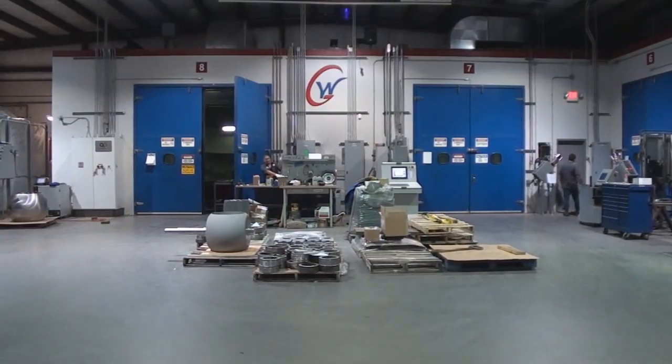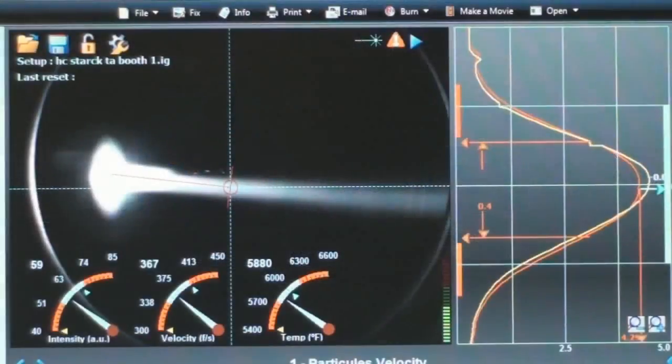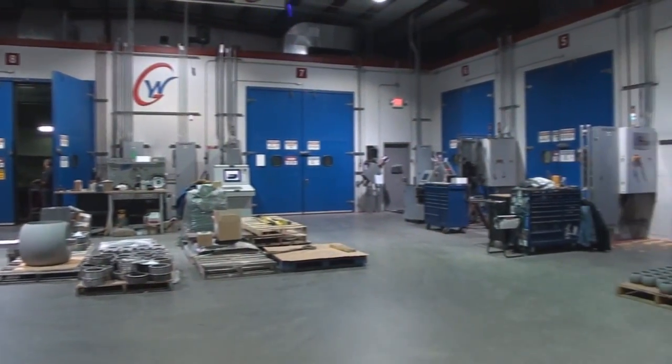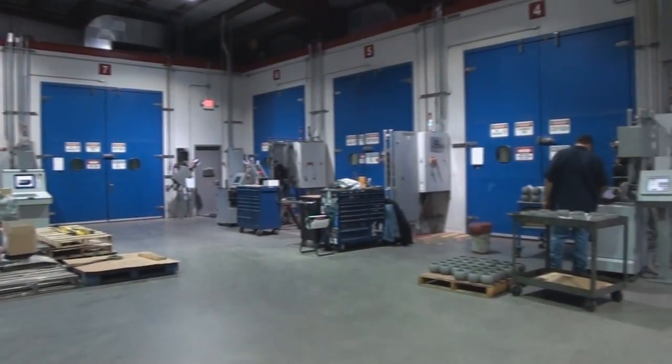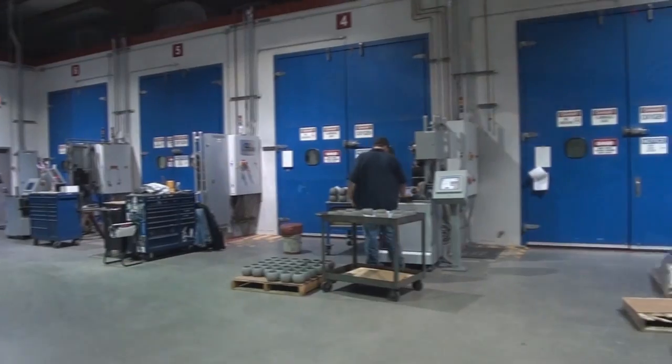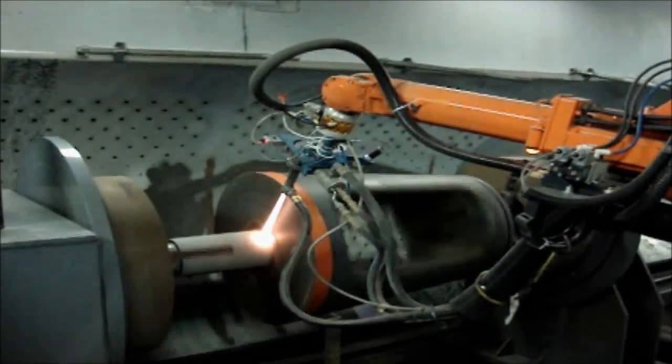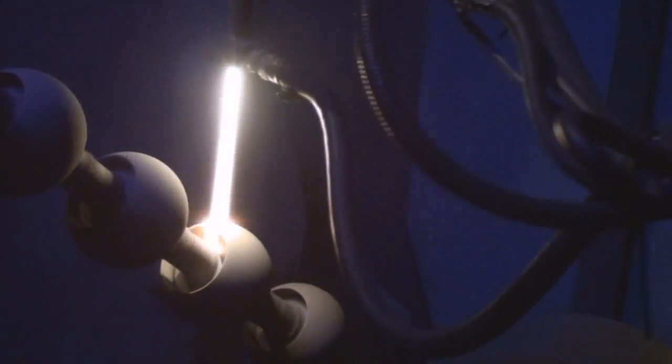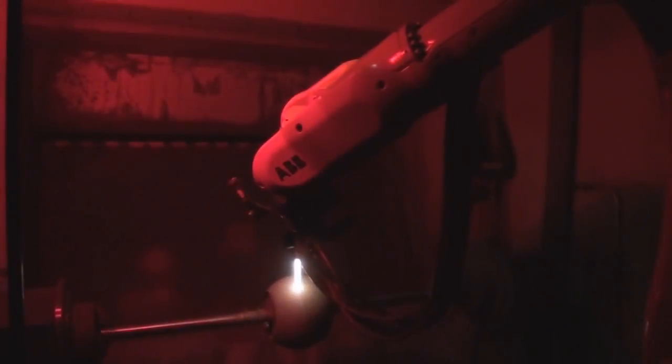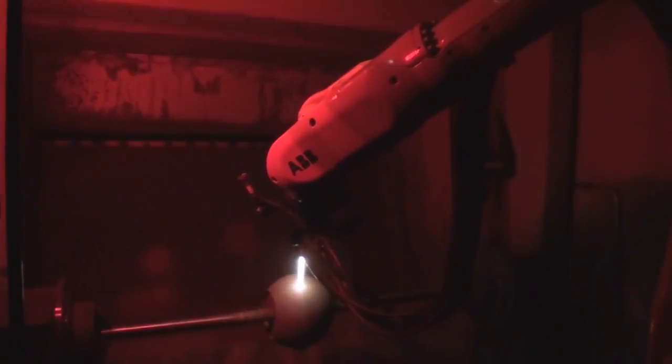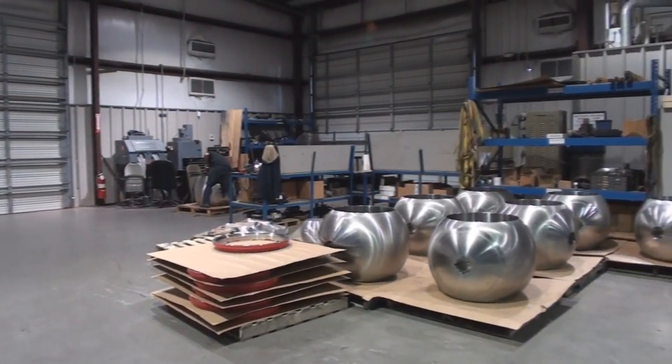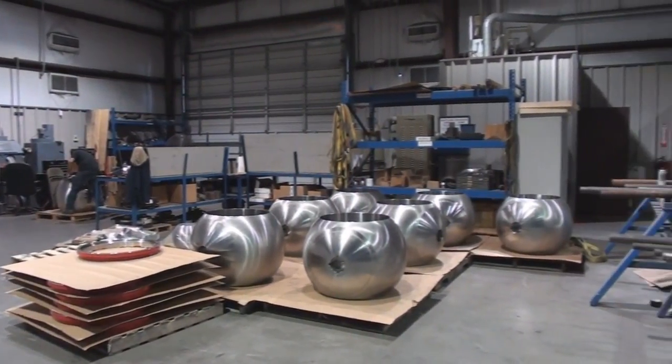As part of our commitment to quality coatings and efficiency, we utilize the AccuraSpray Plume Sensor System in our robotic thermal spray facility. This system provides a real-time evaluation of the average particulate temperature, velocity, and flow rate during the coating process. The vertical position and profile of the plume are recorded and compared to predetermined tolerances. Our experience has shown the reproduction of quality coatings depends heavily on the ability to monitor and control these key variables.